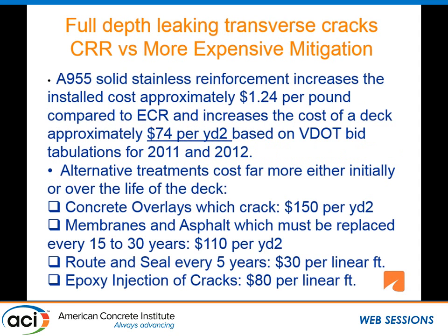Now, solid stainless: we've been using solid stainless since 2010. It increases the installed cost of rebar by $1.24 per pound on average in Virginia, compared to epoxy, which increases the deck cost by $74 per square yard. This is from 2011, 2012 bid tabulations. Alternative treatments really cost quite a bit more.